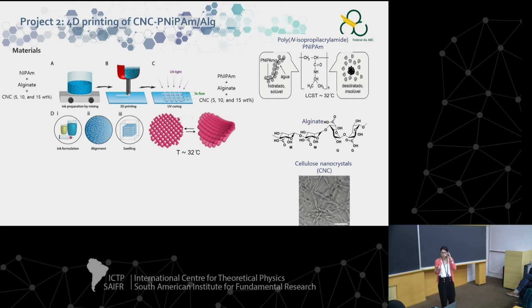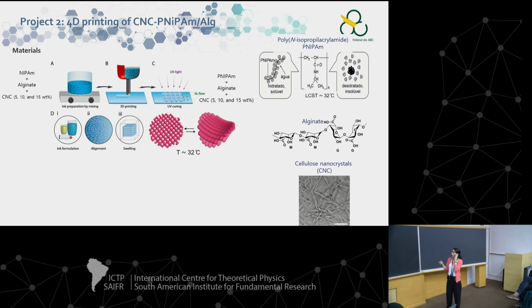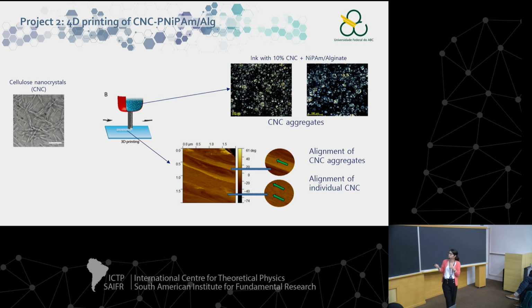In this project, we wanted to use an anisotropic nanoparticle, which is cellulose nanocrystals. We mixed all of them, then placed it in the syringe and printed it. In this mixture, the CNC are randomly orientated, and when it experiences shear stress, these little rods align with the shear stress. So in the filament, we expect an orientation of the CNC along the direction of the filament. Due to this anisotropy, we have different swelling in the two directions, and this ends up with this shape morphing.